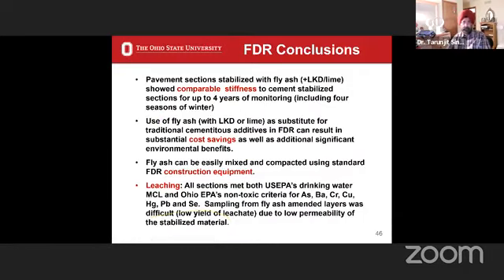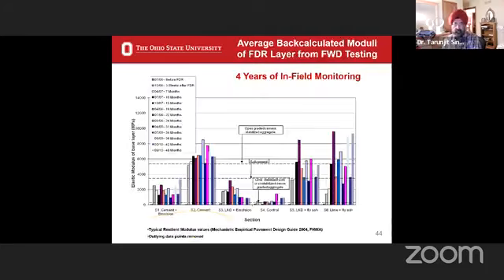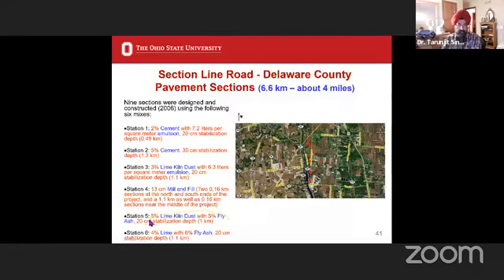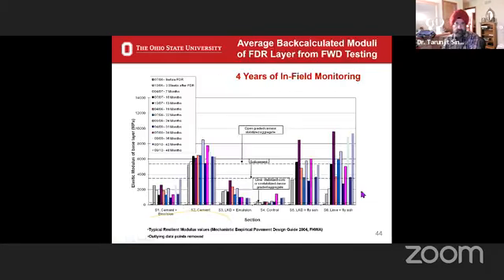Here are the conclusions from the work: the pavement sections for full depth reclamation made with fly ash and LKD or lime show comparable stiffness to the cement stabilized section up to 4 years. And we went through four seasons of winter. The use of fly ash along with LKD or lime can provide significant savings. For example, in these mixes, station 5 and 6, there is no cement whatsoever. It's a cement-free mix.